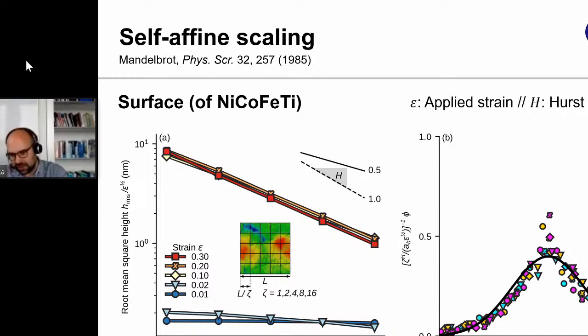So we can rescale all heights such that they are normalized, and we see that during the whole deformation process we can collapse the full height information onto a single master curve, and from this, of course, inversely we can predict how the height distribution evolves as a function of scale throughout these calculations.